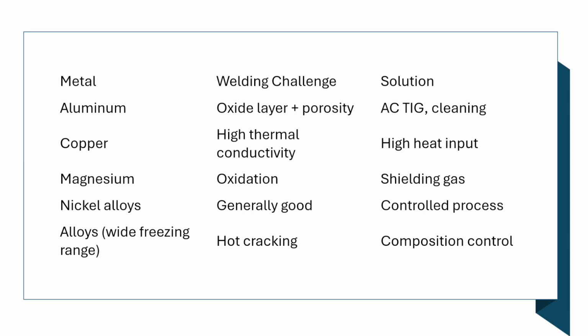So some of the key points are these. Aluminum: what is the problem we face? Oxide layer and porosity. What is the solution? AC current and cleaning. Copper: high thermal conductivity. How can we avoid it? High heat input or providing an insulating blanket. Magnesium: oxidation is the major problem. So how can we avoid it? Providing the shielding gas. Nickel alloys: generally good control of the process. Alloys with a wide freezing range: hot cracking, solved by compositional control.